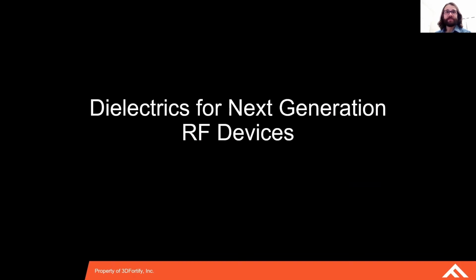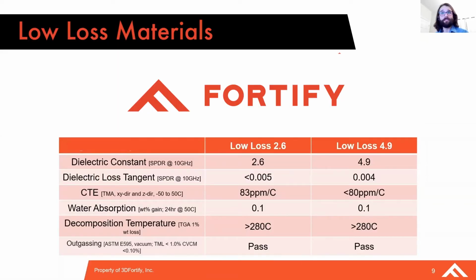But now, with the materials we are discussing today, the dielectrics are ready for the next generation of RF devices. These materials, which are heavily filled with RF ceramic additives, have carefully selected dielectric constants with impressively low dielectric loss tangents. The data presented here is captured and tested at 10 gigahertz. With this development, Fortify brings on two impressive material systems targeting high-resolution, low-loss devices.